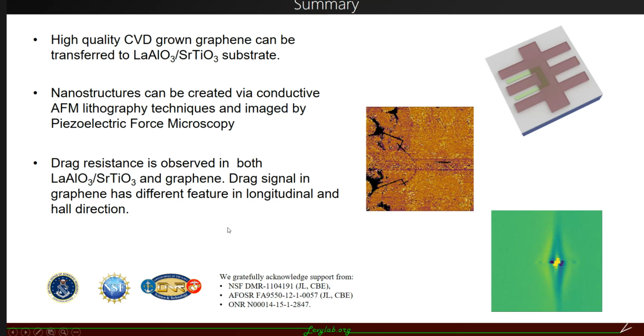So for a short summary, we grew high quality CVD graphene and then transferred it to LAO/STO, and we can create nanostructures by using the conductive AFM lithography technique. We observe the drag resistance in both LAO/STO and graphene, and the drag signal in graphene has different features in longitudinal and Hall directions. Thank you.